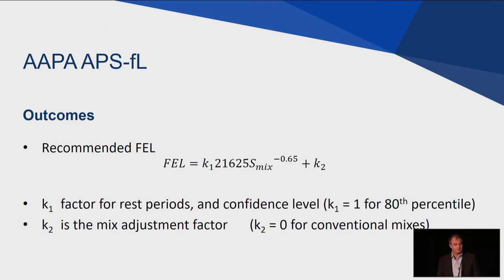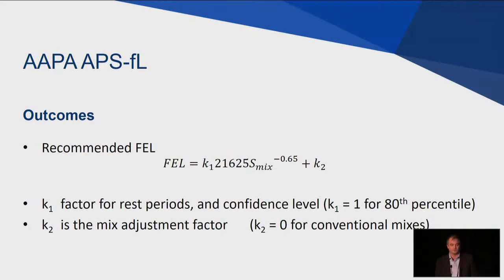So that was a lot of work. And the final outcome: AAPA recommended this fatigue endurance limit for inclusion in the Austroads design method. It's the function that's shown here, where K1 is equal to 1 for the 80th percentile, and K2 is an adjustment factor, which is 0 for conventional mixes. So basically the fatigue endurance limit just becomes a function of the stiffness or the modulus of the mix.